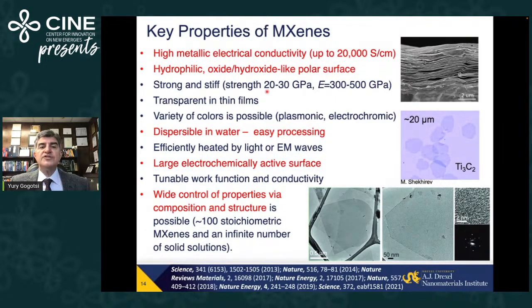Moreover, they're actually stronger and stiffer than all other solution processed materials. An ideal flake of graphene, if you take it here, will have higher tensile strength. But no one makes composites or battery electrodes or current collectors from perfect single crystal graphene produced by peeling off from a large crystal or CVD. People do it from graphene flakes, from graphene oxides. And MXenes are stronger. You can see here roughly 20 micron flakes of titanium 3C2. You will never find a single layer. Those are single layer flakes produced from solution, deposited on a silicon wafer.